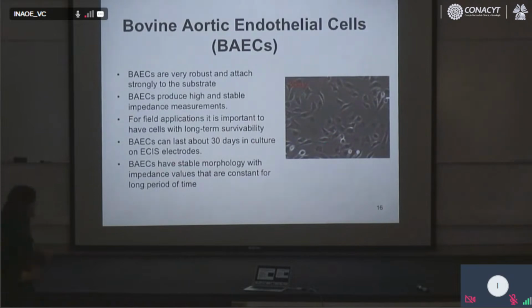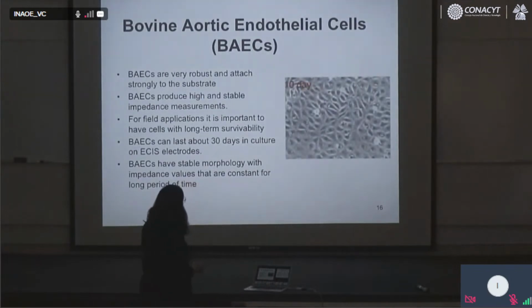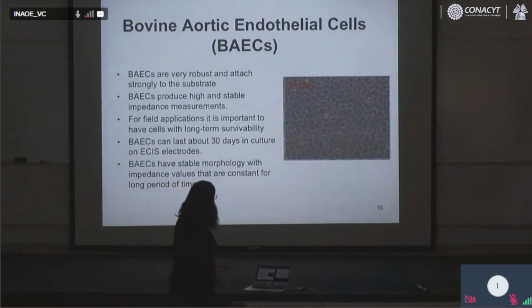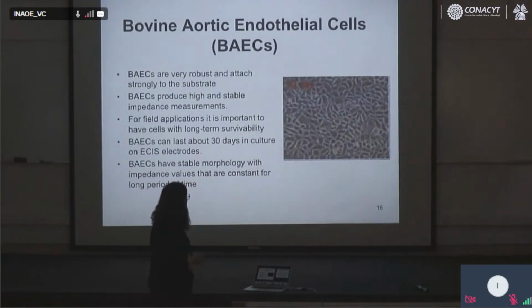And this is the way the cells look. On the third day, see how laborious it is. You cannot do the testing immediately. You need to wait at least 3 days until you form a monolayer of the cells, and then you can start. This is the 10th day, then the 22nd day, the 30th, and then the cells are dying after about 30 days. They are not happy.